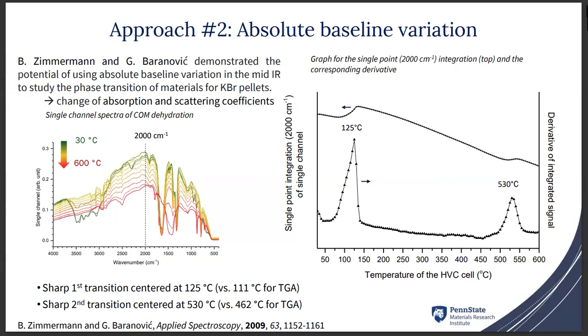If we plot just the value of the baseline over the range of temperature and plot the derivative, we figure out the two transition temperatures, one at 125, one at 530. This first transition is sharper than the previous one, giving a more accurate view of the temperature inside.